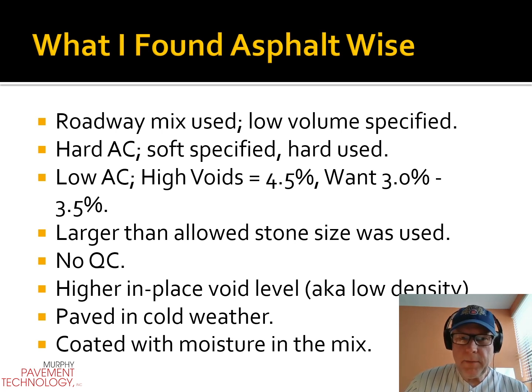In the Canadian item, again, similar. Roadway mix was used, hard asphalt, very high air voids, poor density, no quality control. The extra phenomena that caused problems was it was paved in cold weather, and then it was coated in the spring, and there was still moisture in the mixture, which caused rapid deterioration of the coating. It also allows for what we call stripping. That's when the asphalt pulls away from the aggregate, and essentially the asphalt begins to disintegrate in place, and it will not last 20 years as expected. And this is really a phenomena we can address by higher AC contents and higher compaction values.